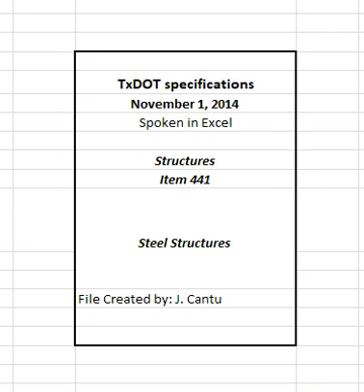Clean and galvanize this test specimen using the same conditions and procedure that will be applied to the production galvanizing. Examine the test specimen after galvanizing. There must be no evidence of excessive buildup of zinc coating over the weld area. Excessive zinc coating buildup will require modification of the galvanizing procedure.